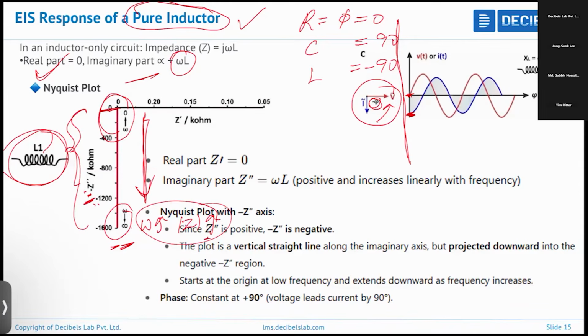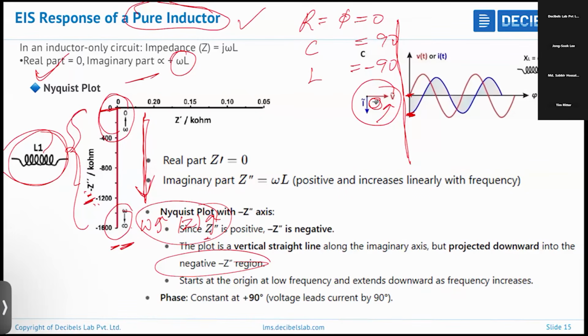Since Z double prime is positive, minus Z double prime is negative. The plot is a vertical straight line along the imaginary axis, projected downward into the negative region. It starts at the origin at low frequency and extends downward as frequency increases. Since the phase is constant at plus 90, it means that the voltage leads current by 90 degrees.